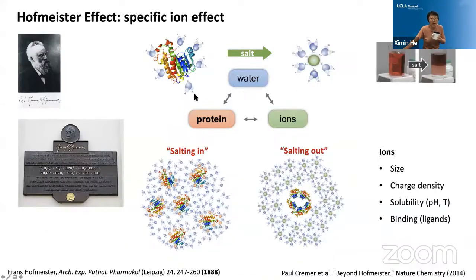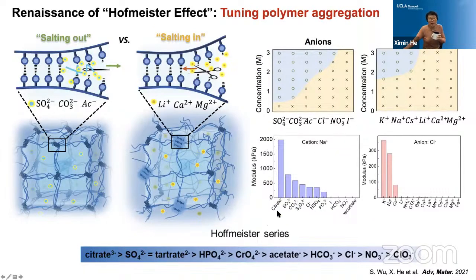This Hofmeister effect is also called a specific ion effect, which describes the different degree of ability of different ions to stabilize proteins depending on the size or charge density, solubility or binding ability between the ions and a different type of protein. This kind of phenomenon has been used very popularly in the industry of protein separation. And then we thought, if this works with protein, the natural polymer, how about a synthetic polymer? Maybe it can help with tuning the mechanical property of the hydrogel by using different kinds of ions. Indeed, experimentally, we proved by using different cations or anions, we are able to tune the Young's modulus or the stiffness of hydrogels across a broad range.